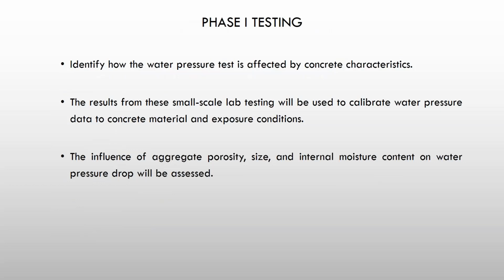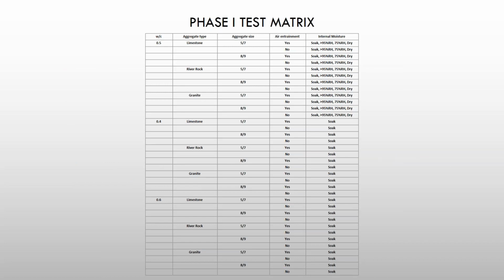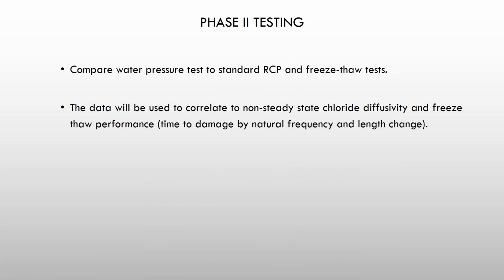During phase 1, we're going to identify how the water pressure test is affected by the concrete characteristics. The results from this small-scale lab testing will be used to calibrate the water pressure data to concrete material and exposure conditions. The influence of the aggregate porosity, size, and internal moisture content on the water pressure drop will be assessed. This is the test matrix where we're varying the water cement ratio, the aggregate type, aggregate size, air entrainment, and internal moisture for the phase 1 tests.